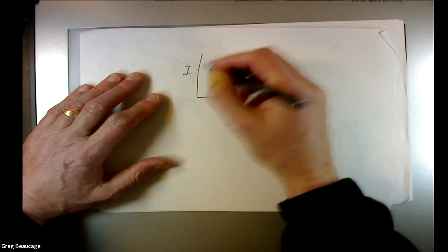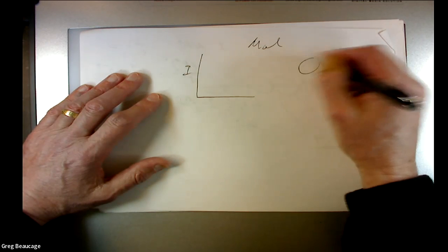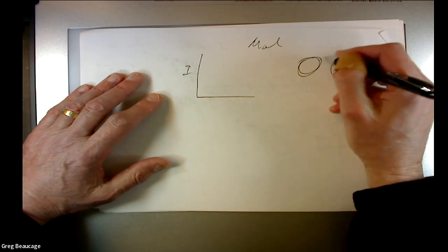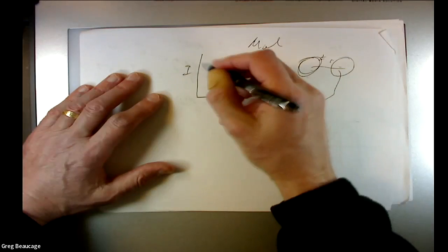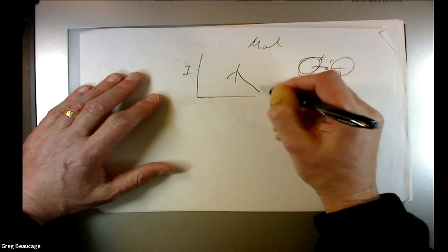So they have this thing, it's for micelles. Micelles correlate with each other because they have some kind of charge on the surface. You get this kind of correlated structure. So that means you get a peak in scattering, but it's disordered. It's going to be like a -4 power law, then it's going to be like a Guinier law at some point.